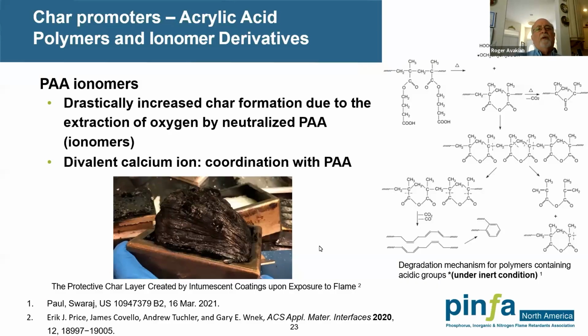So other char promoters, as we already alluded to, were acrylic acid salts and other ionomer derivatives. You can see some of the mechanisms here on the upper right-hand side of the slide. Typically, these polyacrylic acid ionomers drastically increase the char formation due to the extraction of oxygen by the neutralized PAA. This is basically some of the mechanisms postulated here. Again, not all of them work the same way, and you typically need to have some sort of salt. Acrylic acid itself is not going to work. You need to have some salt, and it has been seen that you do see some differences, whether it be, let's say, a monovalent salt or a divalent salt like calcium. And I've seen examples where zinc works very well in coordinating with the polyacrylic acid. And you can see that in the diagram here.